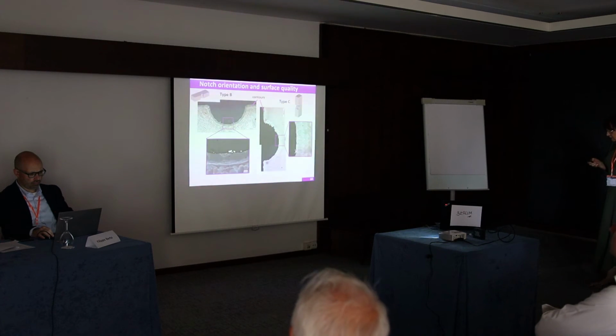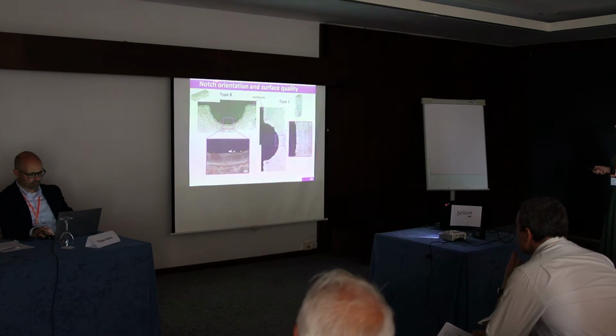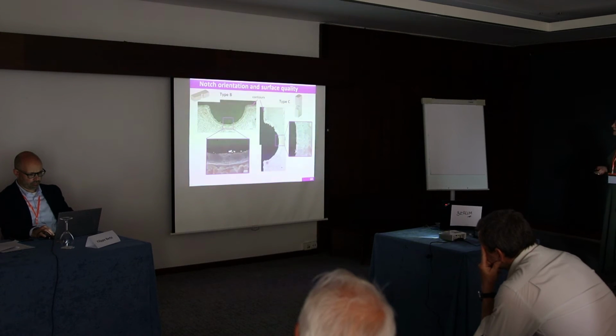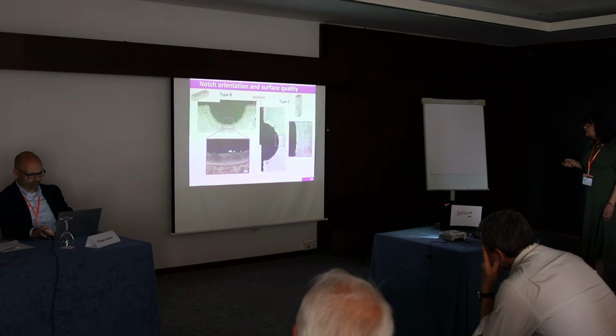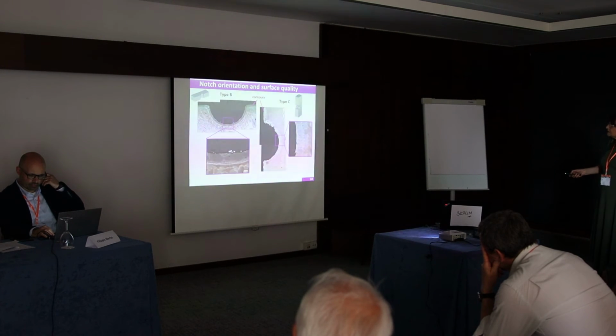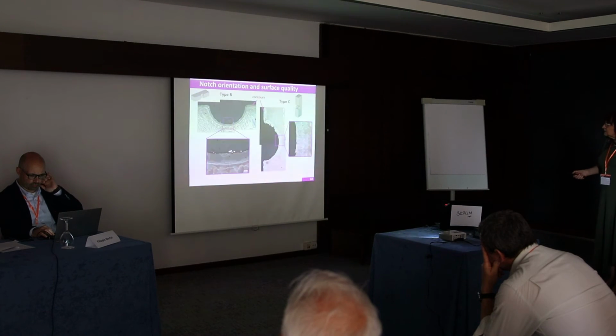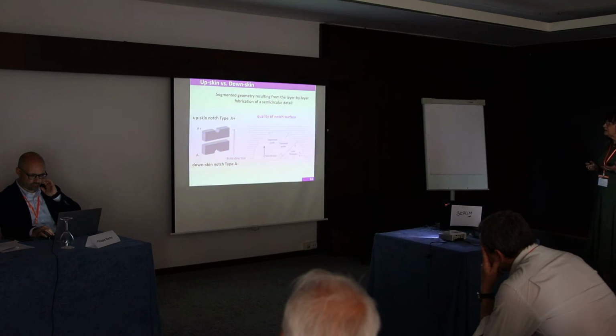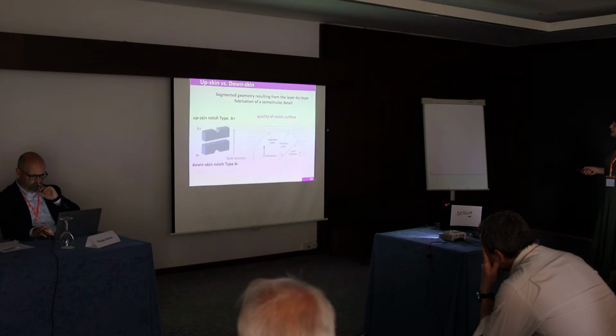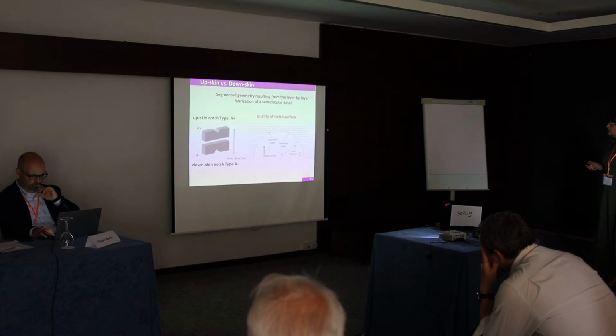Here we can see at small magnification a detail of the notch, and this is type B. Here we can see that it is flat. When we look at specimen C orientation, we can see that here is good roughness, but here is very high roughness. So this is a detail of this part. And the upskin and downskin, which are shown on types A plus and A minus, correspond to this explanation of how the notch is built. So the quality of the notch changes with the direction of build orientation.